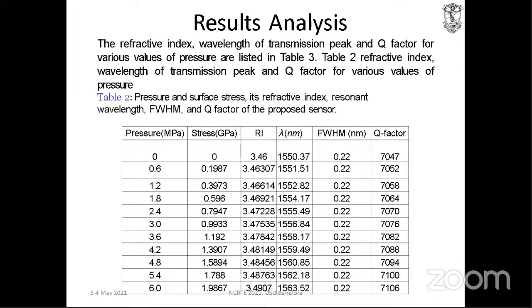For 0, it is 3.46 refractive index and the wavelength is 1550.37. For 0.6 megapascal, the refractive index changes from 3.46 to 3.46307 and the wavelength changes to 1551.51 nanometer. For 3 megapascal, 3.47535 is the refractive index. Because of the change in refractive index, you get a shift in the wavelength, 1556.84. Like that, you can calculate.